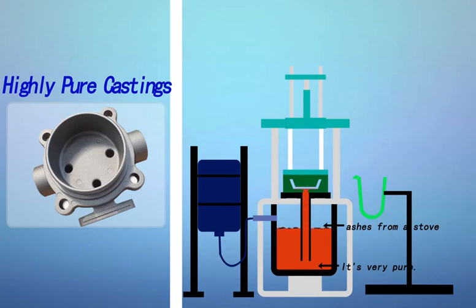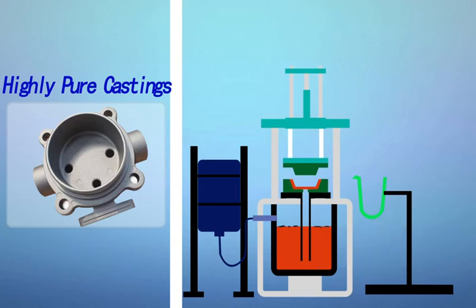Typically, slags are found on the surface of molten metals. Since the riser tubes in low-pressure casting go down into the holding furnace, the liquid metal that is forced into the mold cavity does not contain slag. This results in highly pure castings, further aided by the low-pressure process. Low pressure reduces the chances of slag entering the mold.